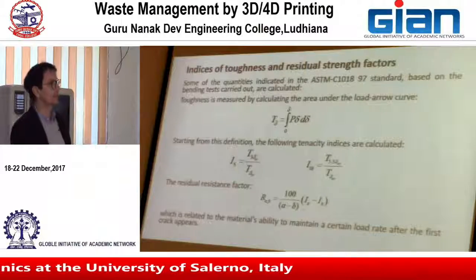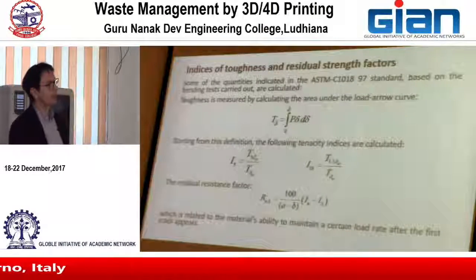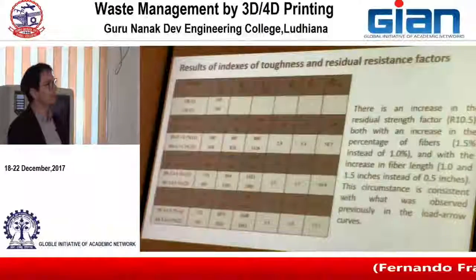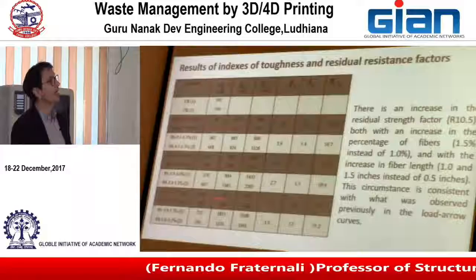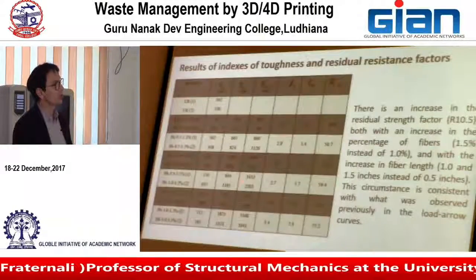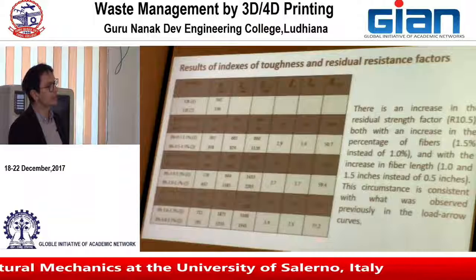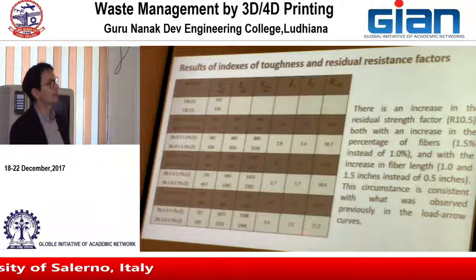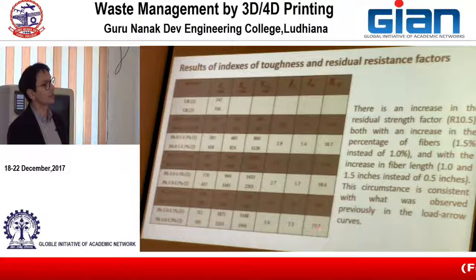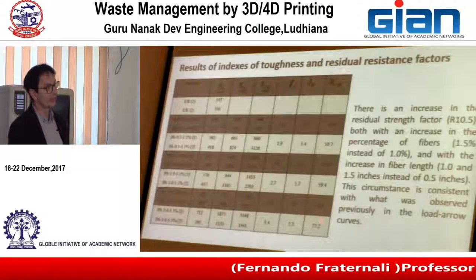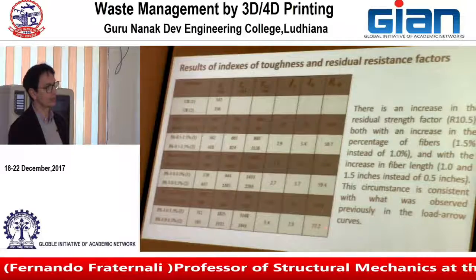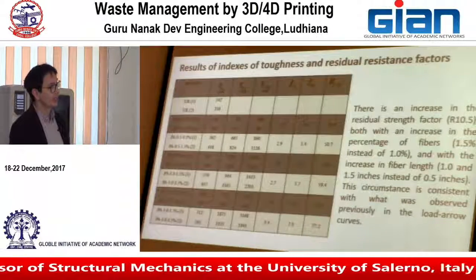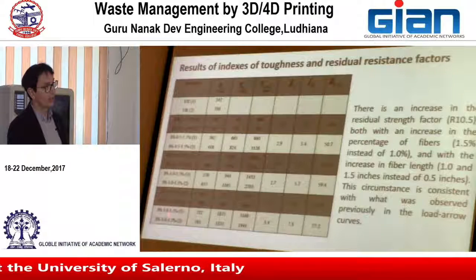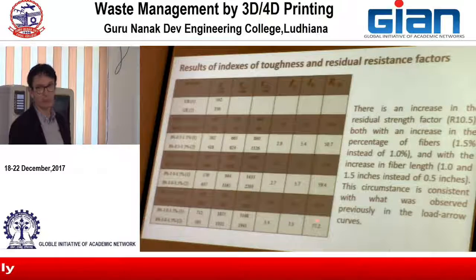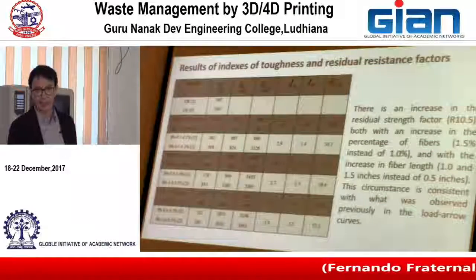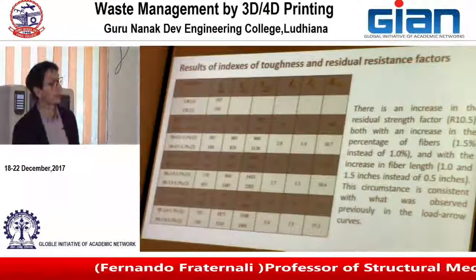We measured the toughness of the materials, by measuring the energy absorption capacity in the load displacement curve. And in this case, we obtained also, those are the utility indices. You can look at those numbers. This is the reduction of the strength post crack propagation. And you see that in this case we obtained a 77% recovering of the crack strength after crack onset.